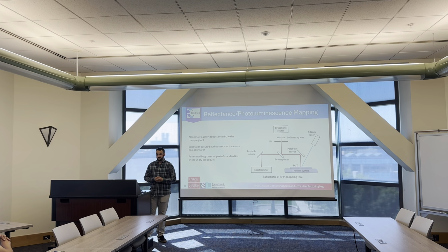So there's some inline characterization that's done by the grower as part of the foundry process. So reflectance and photoluminescence mapping. So I've got a schematic there for a Nanometrics reflectance PL wafer mapping tool. So there's a broadband source for the reflectance measurement, a 532 nanometer laser for the PL measurement, and then the spectra are measured at thousands of locations on the wafer. And as I said, this is performed by the grower.